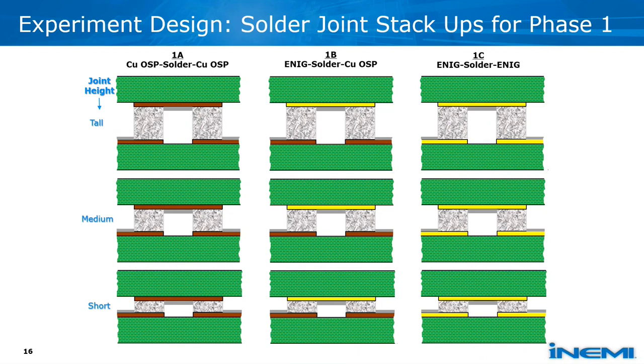And these 3 combinations are also shown here. In one case, for instance, the current will flow from the OSP land through the joint to the ENIG land, and in the other one, it will be from the ENIG land down to the OSP land. So the current direction, which will determine how the bismuth in the tin bismuth moves, will be different for the 2 joints shown here.